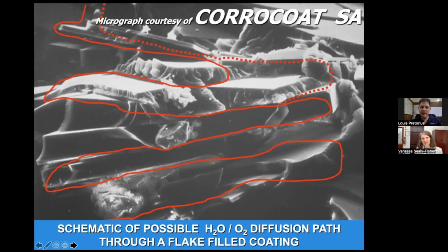And superimposed upon there, the red lines that you're looking at there are possible diffusion paths for a water molecule or an oxygen molecule or some chemical like hydrochloric acid or hydrogen sulfide. So all the small molecules would diffuse through that easier, while something like phosphoric acid or sulfuric acid, which might be strong acids, would be relatively large molecular sizes. So what you see there is actually a thin layer of resin gluing the flakes together. And the way the small molecules diffuse or permeate is only through the resin. They don't go through the glass. Essentially, we're putting in a glass layer and we're holding it there with resin. It's not solid glass, but that's effectively what we're doing.